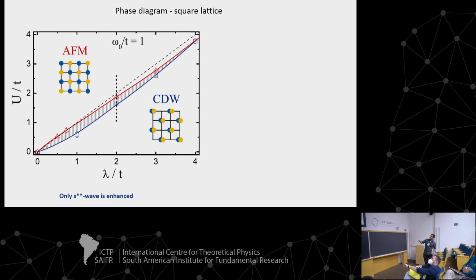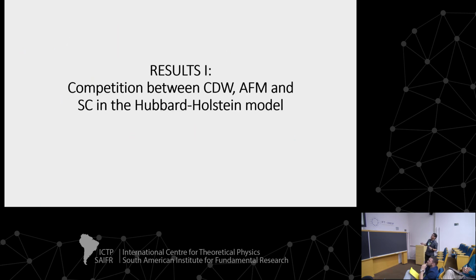So there are just few points here because it's quite difficult to obtain this data. But we are able to create this phase diagram where here we have antiferromagnetism indeed, here we have CDW, but in the middle we have one phase that is neither CDW nor antiferromagnetism. And this phase here, unfortunately, we are not able to present with very precise results about this, but we have strong evidence that we have superconductivity here.